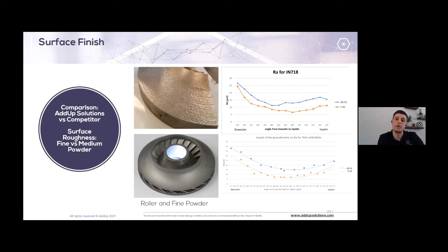So showing here both in Inconel and in Ti64 for a given upskin and downskin. And what I mean by upskin and downskin is the surface as it relates to horizontal. So the bottom surface would be what we call a downskin, and the angle is the relation to it from horizontal. So 90 is a vertical surface. So for any given orientation of your geometry, we can actually improve your surface finish with this combination of roller and fine powder by about 10 Ra, for both shown here in Inconel and Ti64.